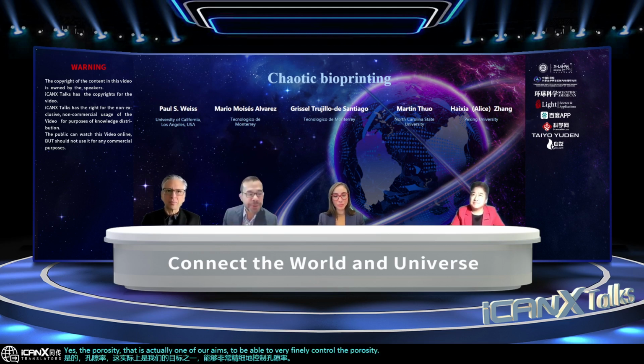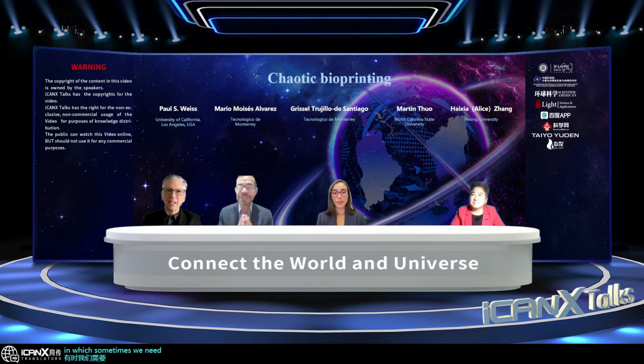Because right now we are exploring diverse bio applications in which sometimes we need sufficient space for small cells, like mammalian cells, 10 microns in diameter. But sometimes we want space for spheroids. And in that case, we are aiming for holes or voids in the order of hundreds of microns and even 1 millimeter. So what we are doing now to control the porosity is two things.